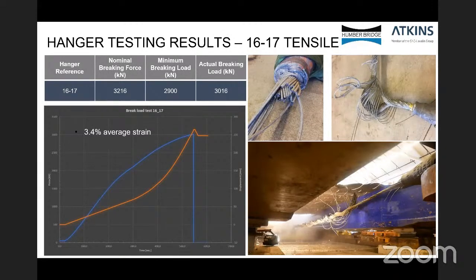The breakage, interestingly, was towards the top, the upper socket, where we suspect the bending stresses will be higher due to the bridge sway. At the top of the hangers, there was only one articulation arrangement, so it had higher bending stresses as opposed to the bottom socket. Again, the breakage results there to the left had a 3.4% average strain, and therefore it passed the results. If we look to the next slide,